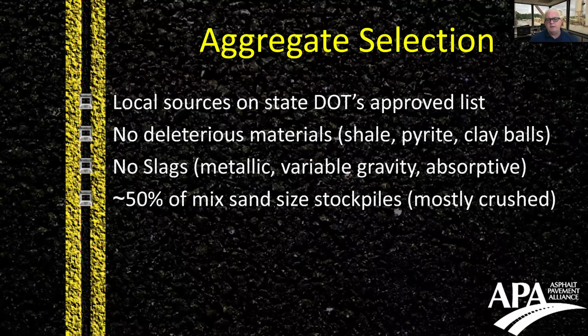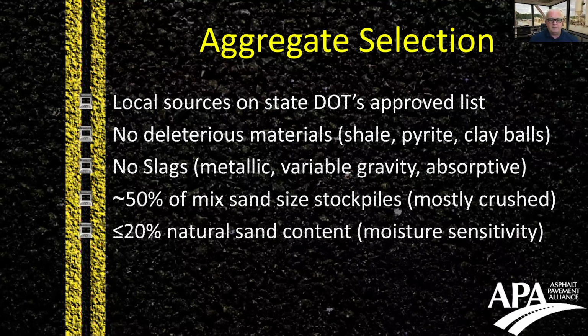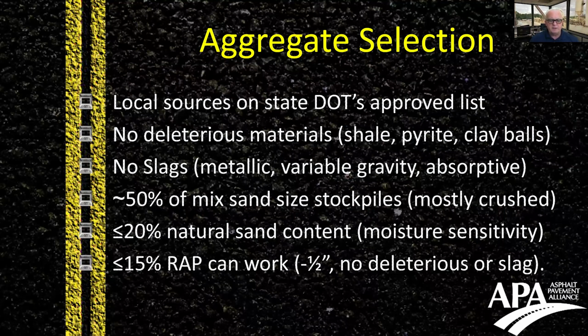About half of the mix is sand size stockpiles. Typically, it's mostly crushed, and that's really because of the size of the mix. Natural sand in this mix needs to be limited to 20%. So you don't need to have more than 20% natural sand in the mix, and that's mainly because of the moisture sensitivity of those materials and the mix tenderness issues that can lead to.